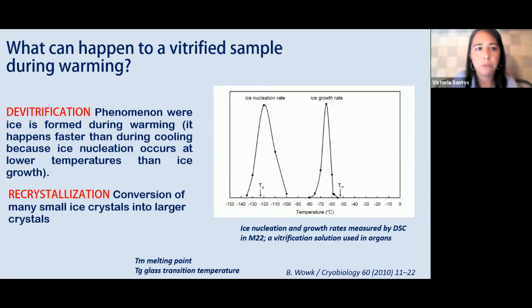So what can happen to a vitrified sample during warming? Well, it can suffer devitrification. This is a phenomenon where ice is formed during the warming stage. And we also have recrystallization, which is the conversion of many small ice crystals into larger ones. These two phenomena occur at different temperatures and at different rates. The ice nucleation rate, for example, is high near the Tg of the sample, and the ice growth rate is high just below the melting temperature.